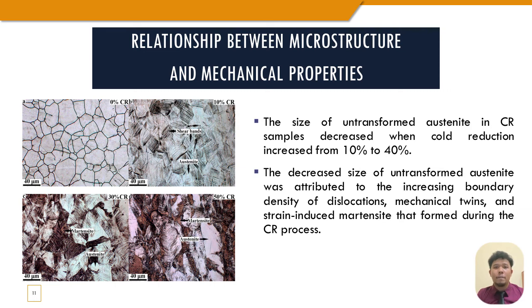Next part is the relationship between microstructure and mechanical properties. So number one, the size of untransformed austenite in cold rolled samples decreased when cold reduction increased from 10% to 40%. The decreased size of untransformed austenite was attributed to the increasing boundary density of dislocations, mechanical twins, and strain-induced martensite that formed during the cold rolling process.